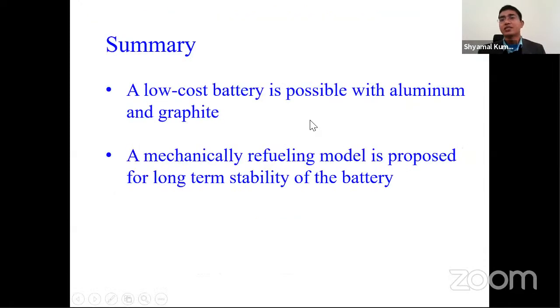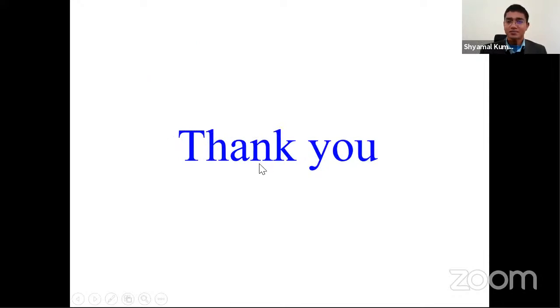So in conclusion, it is possible to have a low-cost battery with just aluminum and graphite, and we can assemble it at our home without any safety problem. Since long-term stability is a big problem in our case, we propose a mechanical refueling model to achieve a large number of cycles and extend the durability of the battery. And it is possible because aluminum is a very, very cheap material. We can buy any number of aluminum foils from the grocery shop at a low cost. With this, I'd like to thank you very much.